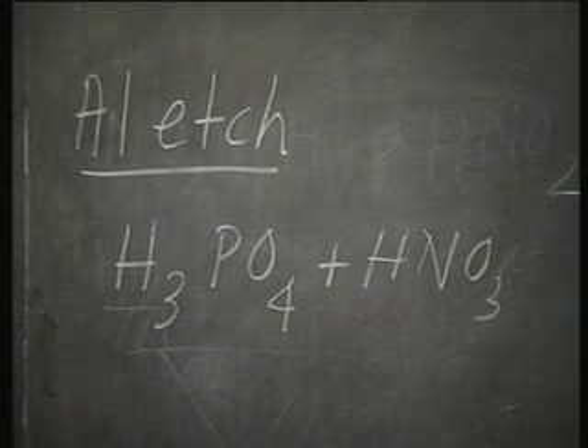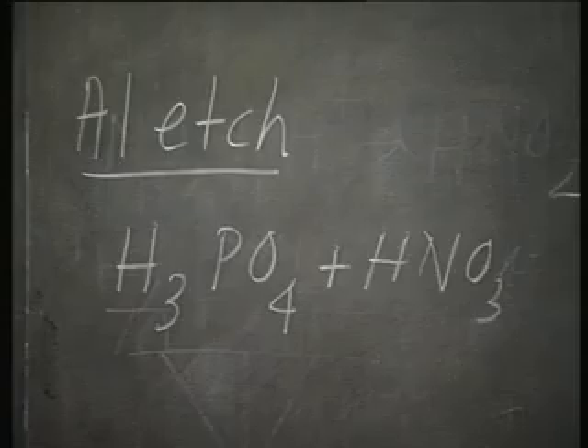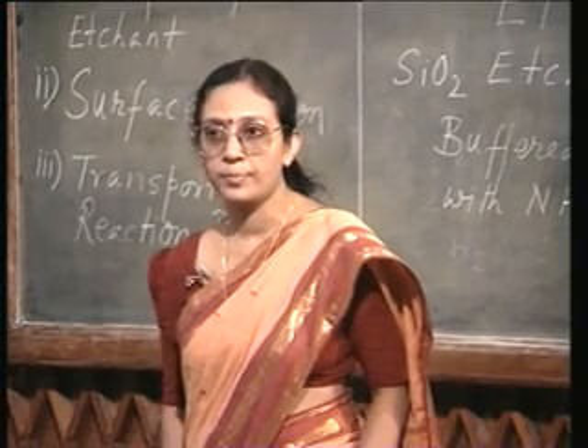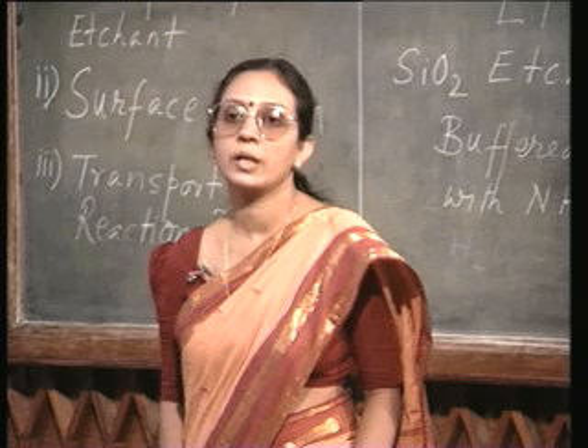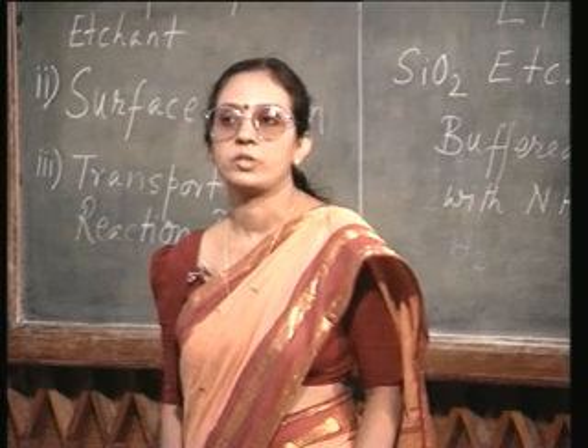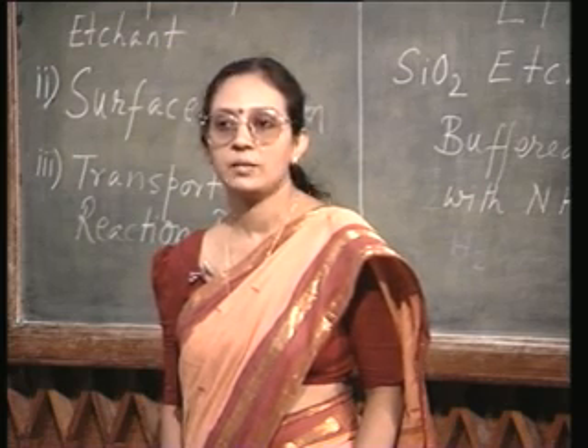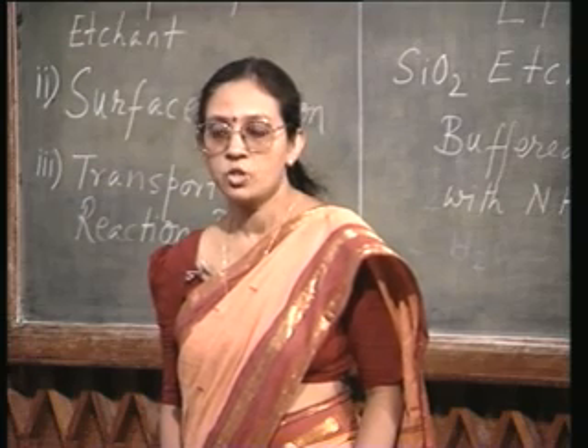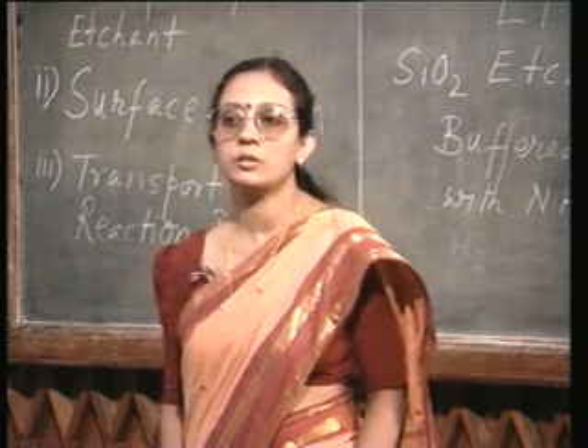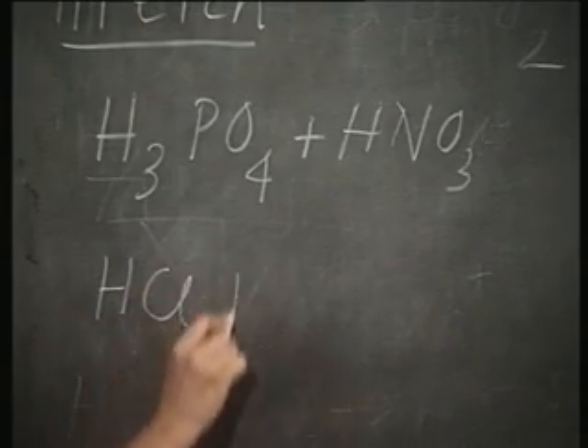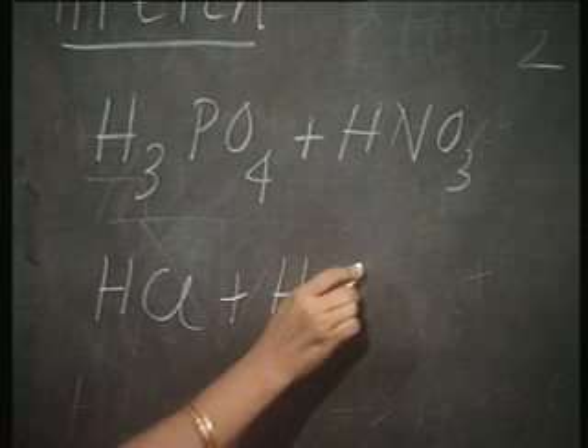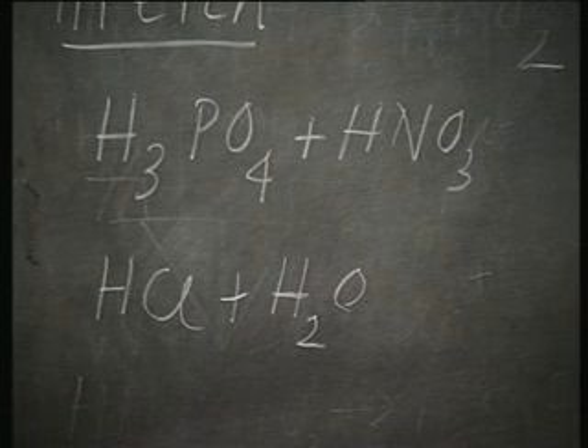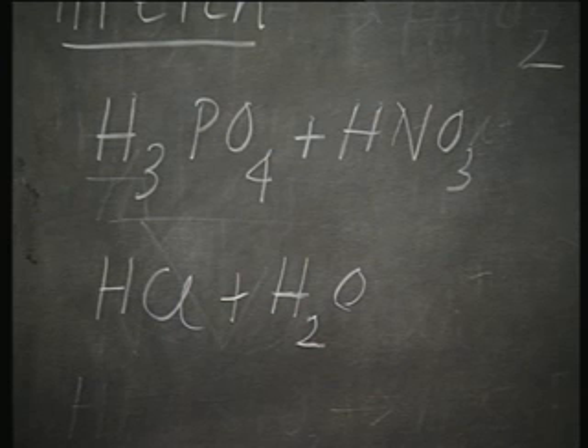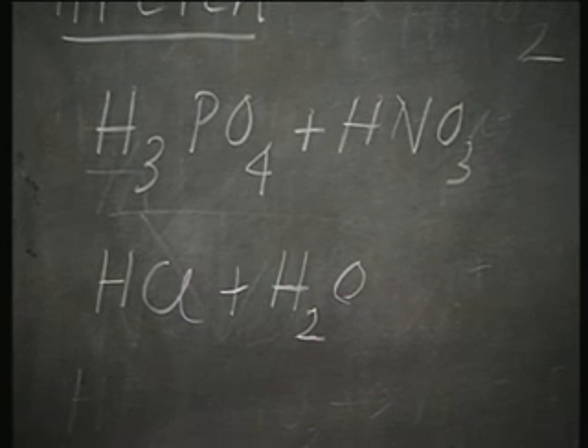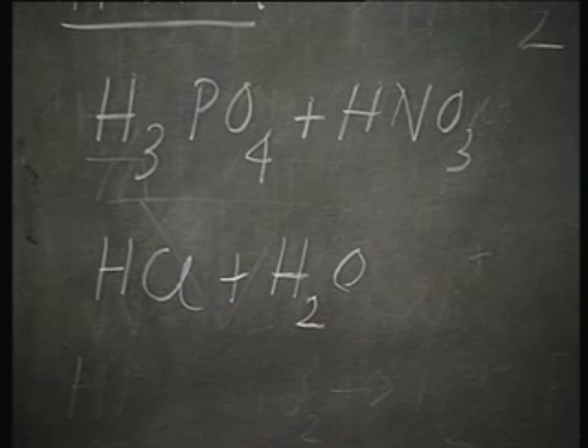But remember, you cannot use it with all kinds of substrates. For example, if you happen to work with gallium arsenide, you cannot use orthophosphoric acid. That will attack gallium arsenide. So, for that you have to go for an alternate solution, that is using diluted HCl. Like I said, it is very simple to remove aluminum. You have to choose an etchant material depending on your substrate which can withstand this.